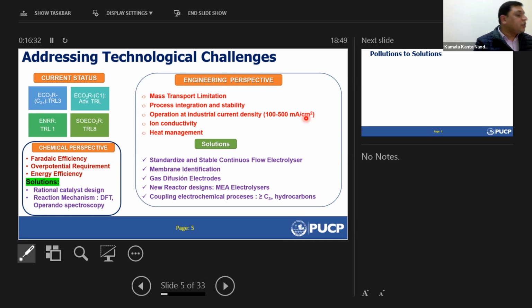And for organic electrosynthesis that occurs in organic solvent, the ion conductivity is the issue. And again, when we are operating the cell at higher current density, there is a lot of heat generated. We have to do the heat management. The solution is to standardize and make a continuous flow electrolyzer, and we have to identify a suitable membrane for a particular process. We have to make better gas diffusion electrodes so that they can resist higher current densities. And further, we can use MEA electrolyzers.